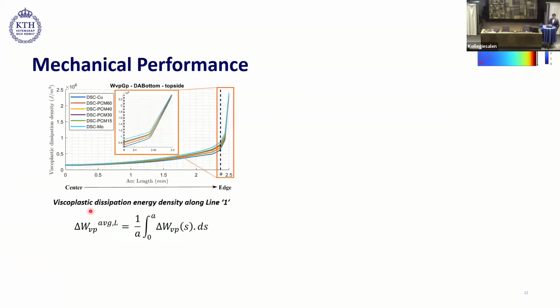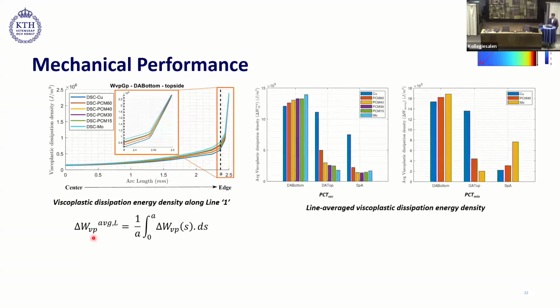Here we are looking at the viscoplastic dissipation energy density along line 1, which is basically this line. And we see that in the central region, the dissipation density is a bit lower, but it increases drastically towards the edge. Therefore, we use the dissipation density in this region, in this formula, to calculate the line average viscoplastic dissipation density. And then here we plot the line average viscoplastic dissipation energy density in different layers for both PCT-SAC and PCT-min. There are a few trends which we can see here.